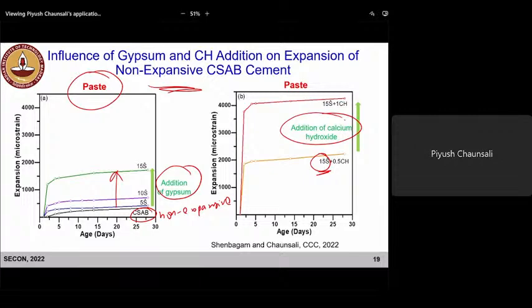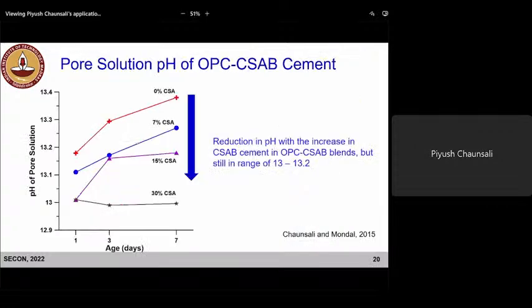We know that when we have more gypsum, we tend to form more ettringite. And also we know that when we have calcium hydroxide in the system, a greater amount of ettringite is formed. But we'll also look at whether there are any changes in the pore structure, right? When we have so much expansion, can we differentiate non-expansive and expansive systems based on the pore structure?